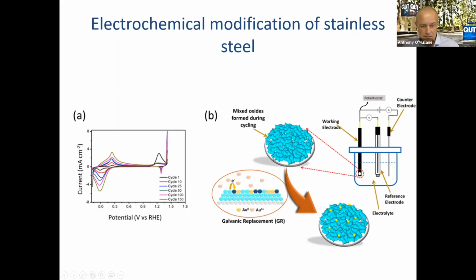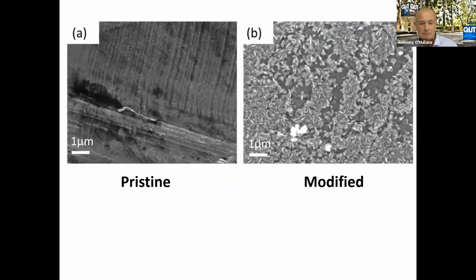So what we did as a further step is that we introduced a little bit of gold into the material as well, by a galvanic replacement process to dope some gold into our modified steel. And the reason for that I will explain in a minute.